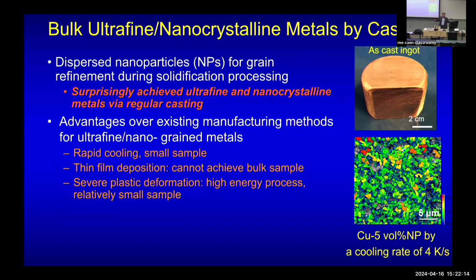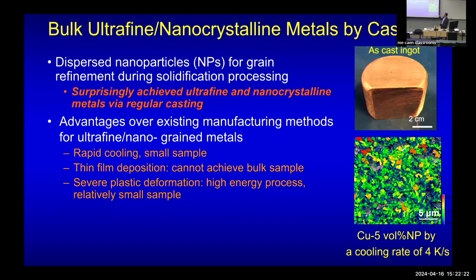But in production-scale casting, nobody can make small grains, especially in larger parts. Surprisingly, in 2015, in pure copper, we put in nanoparticles at a few percent. Just using regular casting, at about 4 degrees C per second, quite slow, between sand casting and permanent mold cooling rates, we found really small grains, ultrafine, even nanocrystalline.